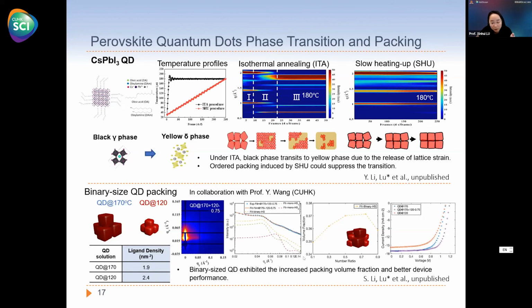And then we find that indeed in the binary mixing film, the packing density, the volume fraction, increases, which leads to the increase of the device performance. And we are in collaboration with Professor Wang Yi in our department to understand why the binary quantum dots can pack better. Intuitively, because we have two different sizes, the small quantum dot can insert into the gaps in the large quantum dots packing. However, I think it's more complicated than this, because the ligand density will also affect the packing.